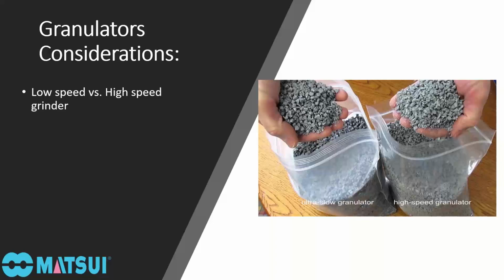An alternative to high-speed grinding would be a low-speed grinder. And a low-speed grinder will cut the material or grind the material at a lower rate of speed. So by doing so, it will reduce the amount of dust and fines generated, and it will also help to create a more uniform shaped regrind pellet, which will assist both with the drying and conveying processes. Also, a low-speed grinder is small enough, quiet enough that it can be used within our injection molding machine cell.